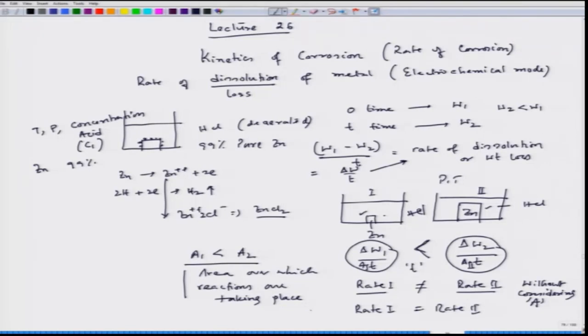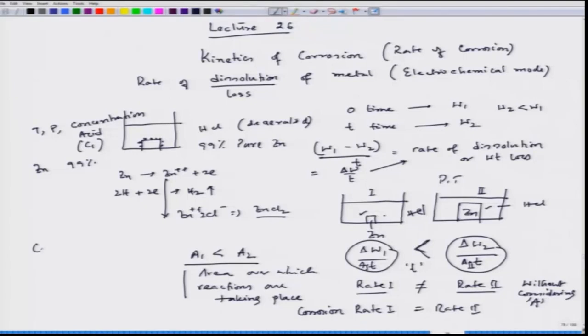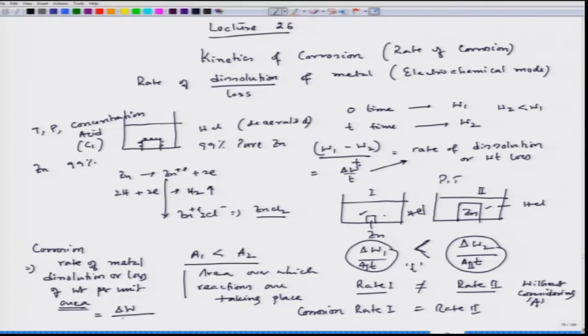So that means the corrosion rate or the dissolution rate of that particular metal per unit area, they are equal. So that means this area is an extremely important factor while we consider the rate of corrosion. And we have to consider that the corrosion rate is nothing but the rate of metal dissolution or loss of weight per unit area. This is an extremely crucial factor, and that means our formula would be del W by A T, or you can say mass per unit area per unit time.